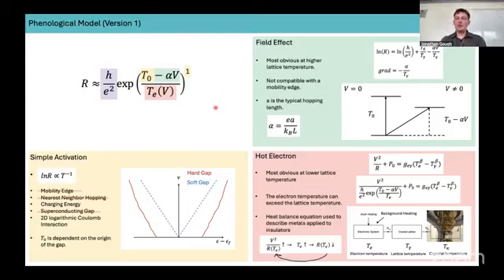We then include two non-ohmic effects in our model. First, this field effect, which accounts for the voltage due to the tilt in the potential landscape. So this tilt effectively lowers your gap size by this term alpha V. This is actually quite nice because this alpha term provides information about the system, notably the typical hopping length A.